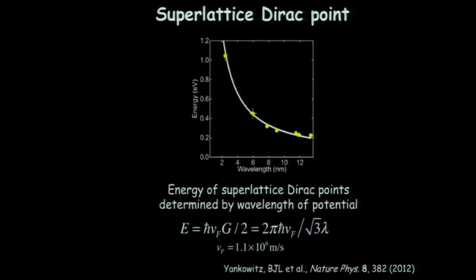So this shows that essentially the boron nitride is having an effect on the high energy properties of the graphene. These are occurring, minimum 0.2 eV away from the Dirac point all the way up to 1 eV away. But we can't actually access anything lower than this because the longest wavelength you can get for graphene on boron nitride is this 14 nanometer wavelength. And so you can't get any longer wavelengths because of the lattice mismatch.